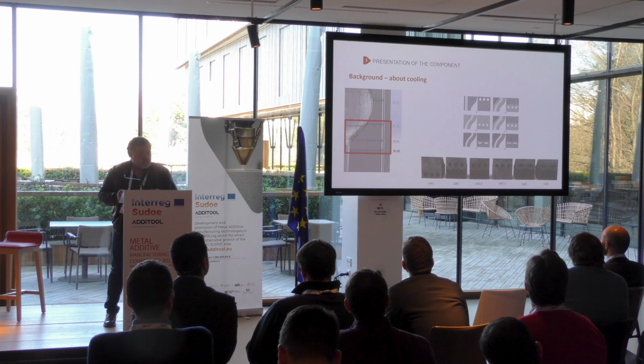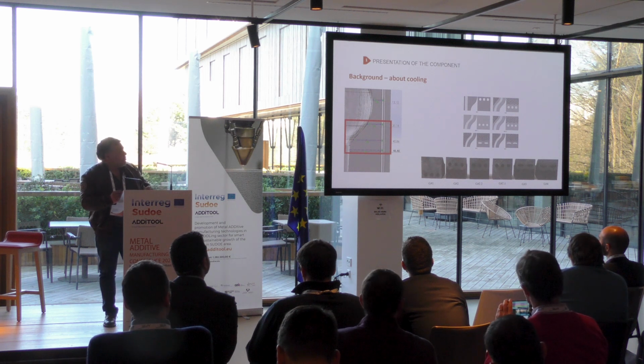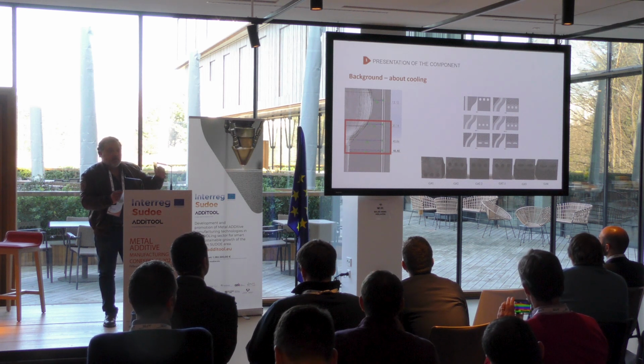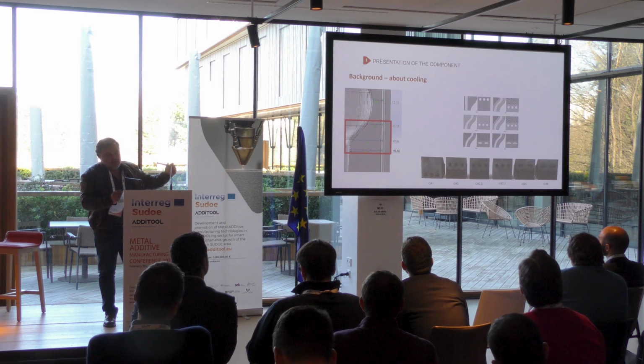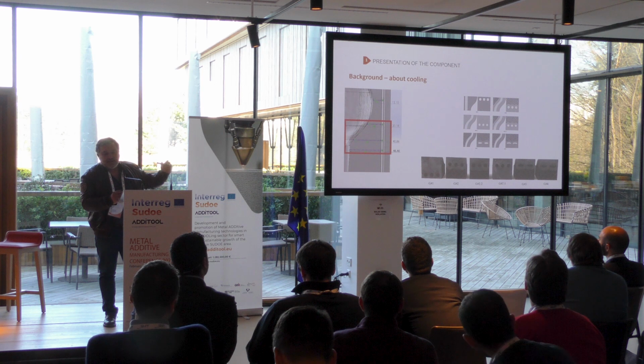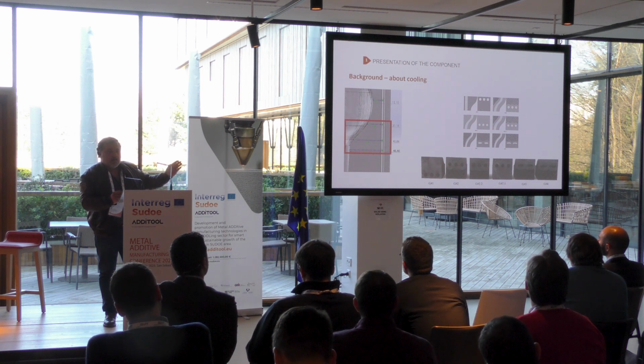Usually the temperatures in the process come from 1040 degrees in the melting state. In the molding state, starting of the tool is around 1000, and then in the blow phase we go down to 600 to 400 degrees.